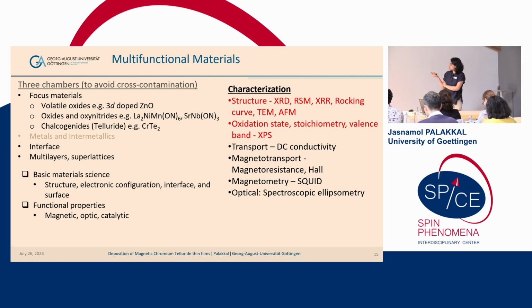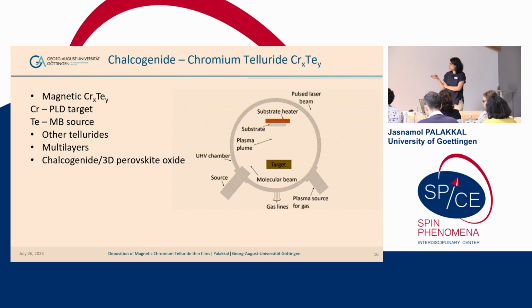But this is also important if you are storing the material in a glove box for a few years. Sometimes you get the best material from the thin film growers and you get really good results, and you keep it in the glove box and investigate it after a few years. But in such cases also the structure or the electronic state could be different after a few years. So always go for such structural characterization before doing advanced characterization.